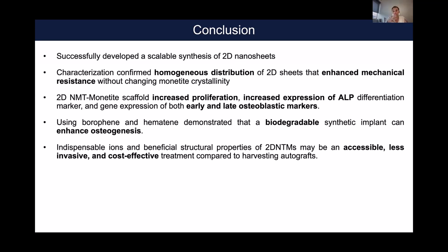Then we showed that by mixing them with the bioceramics, we're able to enhance the mechanical properties of those bioactive cements without changing the crystallinity. And that's important because, if you're familiar with cement, depending on the crystallinity, depending on the ceramic, you will have different resorption. Then we showed that doping the monetite with those two nanomaterials, and I don't make any distinction between the borophene or the hematene, we both saw increased proliferation and increased expression of ALP differentiation marker in the early stage for both, but especially for borophene in the late osteoblastic marker.